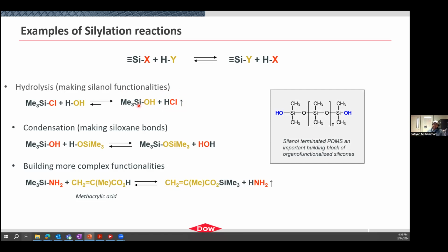Then you can take that same material and actually react it with itself. Now, in one case, you have an OH group as your heteroatom, and in the other case, you have that active hydrogen species. So your OSi group becomes the species that's going to move, and we can change out our heteroatoms and create another siloxane bond here through condensation. Now, you'll see that this reaction isn't driven to one side. These siloxane bonds are very stable, so it's favored to form them. But in most cases, we're using a catalyst here to drive condensation on a faster time scale than what would naturally occur.